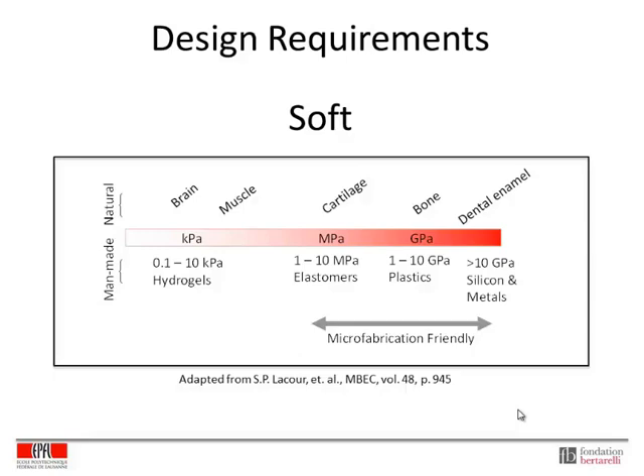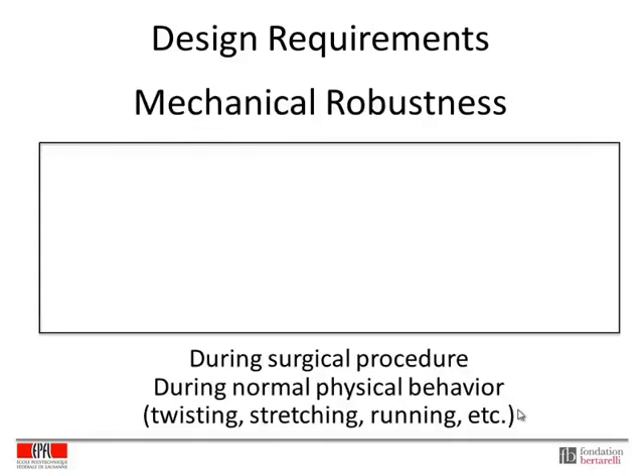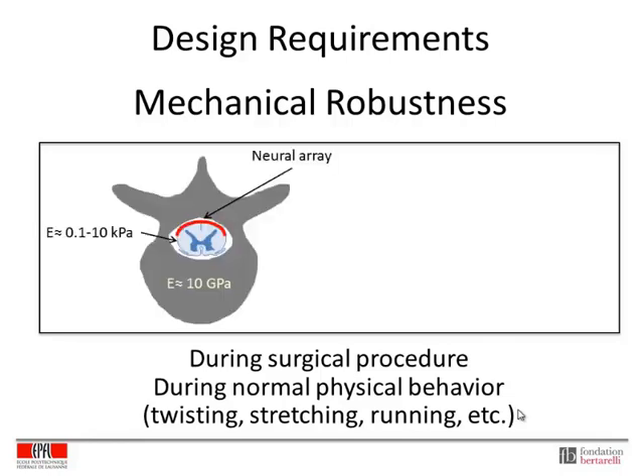So while in our case we use silicone PDMS, and while this isn't a perfectly ideal material for brain applications, it's not as soft as a hydrogel, it's friendly in the microfab, and it's very well known to be biocompatible. Also, in terms of designing soft electrodes for implants in particular, it's really important to note that the electrodes need to withstand stresses both during the surgical procedure as well as the lifetime of the electrode after it's been implanted.